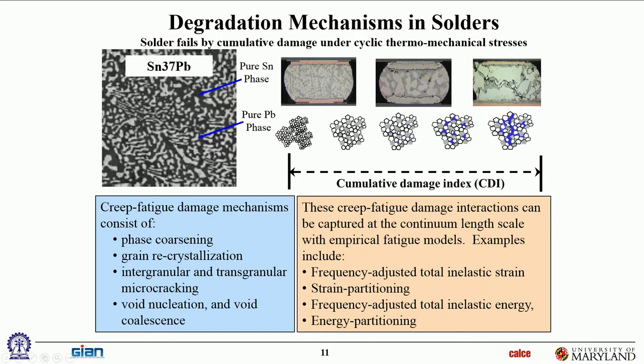The damage at the grain boundaries is happening partially because of mechanical stress that's accumulating there. That's the plastic strain. And then the creep strains are actually causing little micro voids. So some of these are cracks, some of these are micro voids at the grain boundaries. So there are two kinds of damage going on. There's damage due to plastic strains, where dislocations are causing cracks, and there's damage due to the creep deformation, those are the voids forming at the triple corners of the grain boundaries. And then they all join up eventually, and so there's an interaction between them. So the term used for that is creep fatigue interaction damage, okay? That's what you have to account for in high temperature fatigue damage, cyclic fatigue.